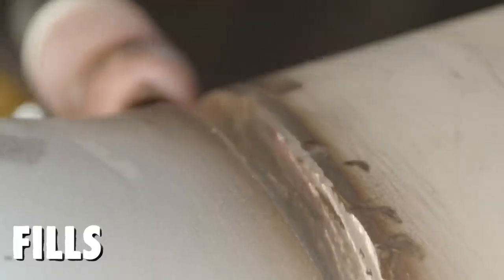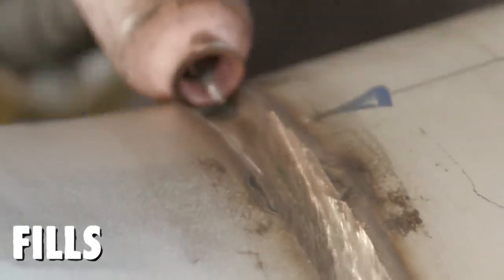And the way it works, say for example, if you have any heat tint on your root pass, the root pass would have been done at anywhere from 25 to 30 to 60 parts per million of oxygen. So even if you had any amount of heat tint, light straw colors, gold, brown, etc., when you put the hot pass on, the hot pass drops down to 11 parts per million or less. It's a really good quality purge.